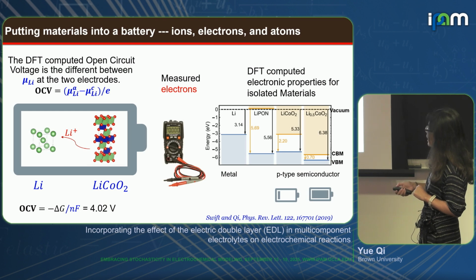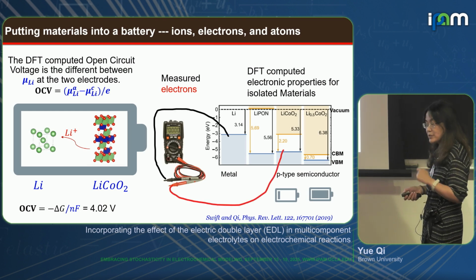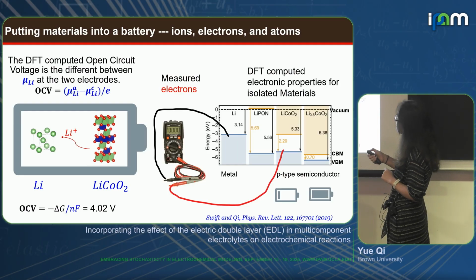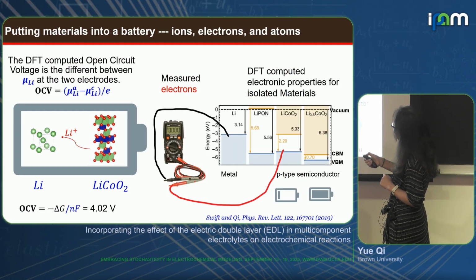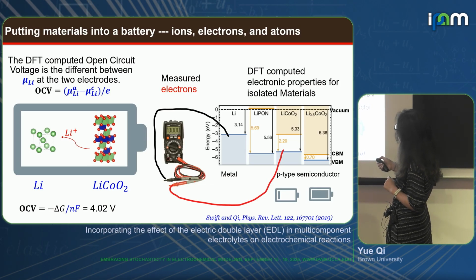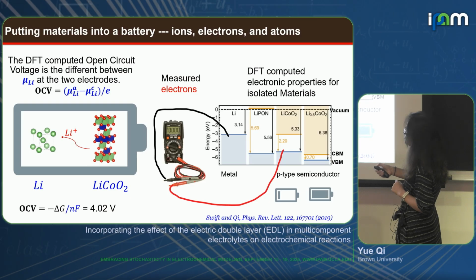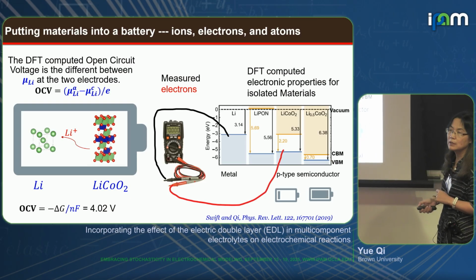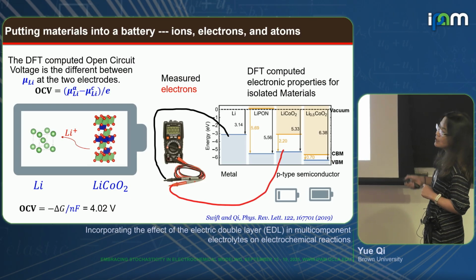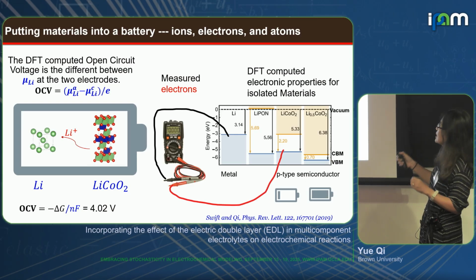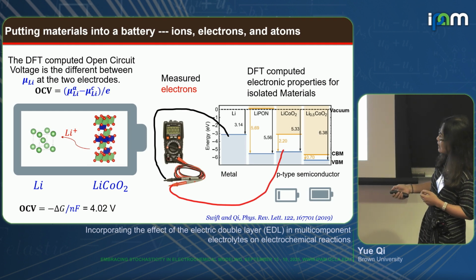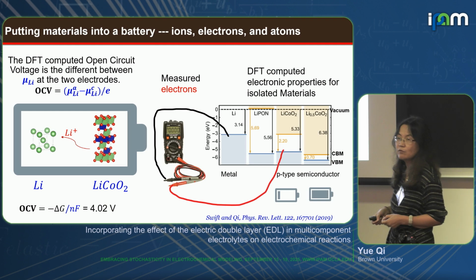But if you measure electrons, right? If we measure electrons, if this is a band level of the lithium, this is a Fermi level of lithium, this is the lithium cobalt oxide. If you take a look, the electron level is about 2 volt difference, not 4 volt. Okay? And that's because those materials are separate. So if I have separate lithium cobalt oxide, the Fermi level difference is about 2 volt. It's not the open circuit voltage that is measured as 4 volt.